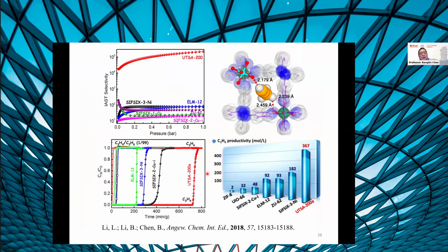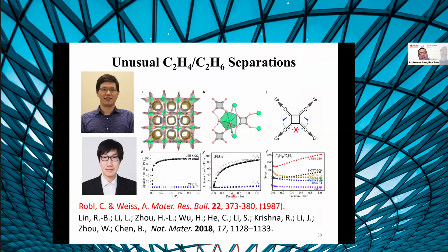Although this is quite good compared. And this is another breakthrough for our studies of MOF material for gas separation. And I should mention that this material, the structure, was reported a long time ago, almost about 1 decade before the establishment of MOF chemistry. However, this material shows unbelievably unusual sieving separations of ethylene and ethane, so very high sieving separation.